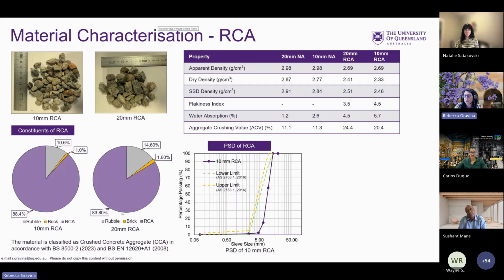And also these constituents, normally the recycled crushed aggregates are a combination of rubble and brick, and also recycled concrete itself. And provided that recycled concrete content is as large as possible, you can guarantee quite a good quality product of that recycled concrete aggregate. There are some supplies of construction and demolition waste that are not suitable to be used for concrete with these sort of target strengths of 40 MPa and above. So that's why this material characterization is very important. And also the particle size distribution, to get a nice particle packing performance through our mixes.